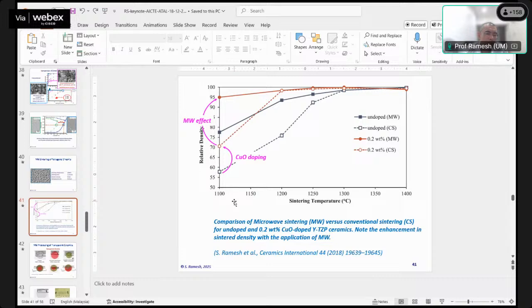So what we did was, you know that if you work with zirconia, it is not possible at 1100 degrees centigrade to get at least 95% dense, right? So part of this PhD work was to try to enhance the low temperature capability of zirconia. That means the sintering capability. So what my student has done is to dope zirconia with copper oxide. With copper oxide doping, if we focus at low temperature 1100, before doping, it is at about 57% dense. With copper oxide doping and sinter at 1100, my student was able to bring up the density from about 57% right up to about 70%.